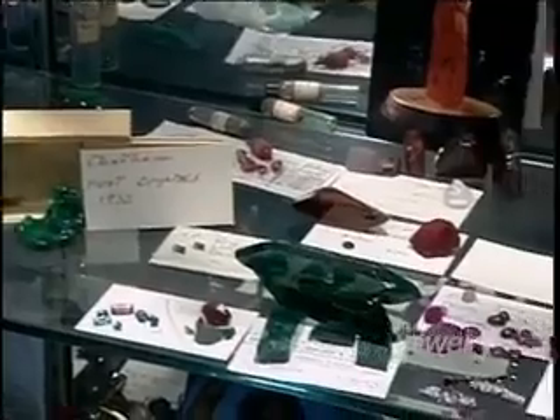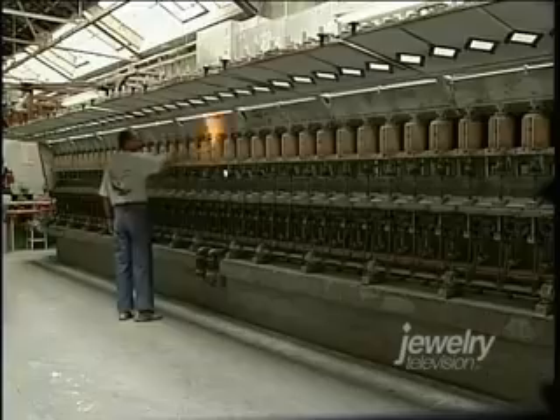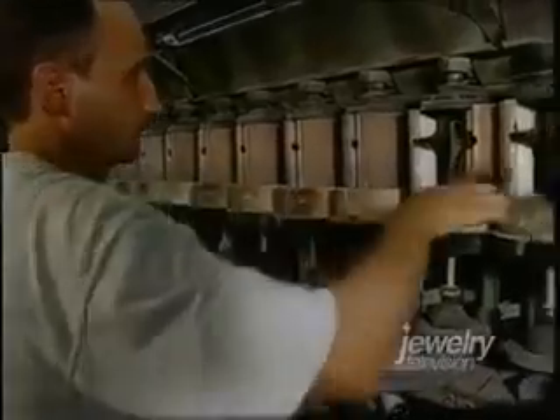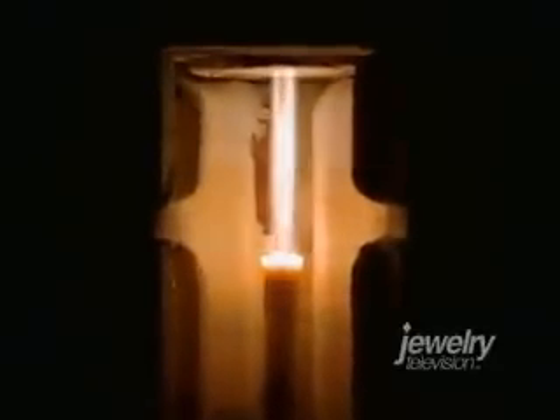But recent scientific breakthroughs have offered an alternative. In 1902, French chemist Auguste Verneuil perfected the flame fusion process, a quick and easy way of creating synthetic gem boules or crystals. Flame fusion is a method that essentially is melting the chemical components that make corundum. You have an oxygen-hydrogen torch that is heating a chamber through which powdered aluminum oxide, in the case of corundum, drops with the dopant of chromium or titanium and iron to give the color.